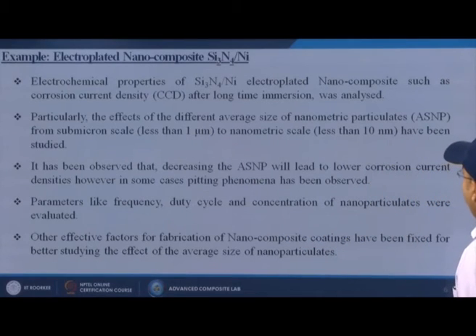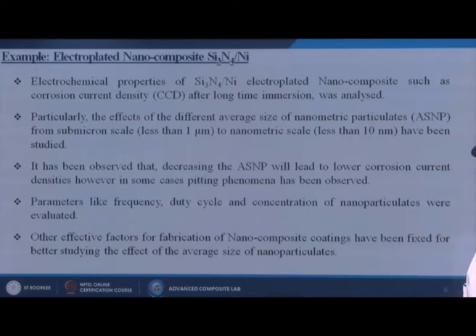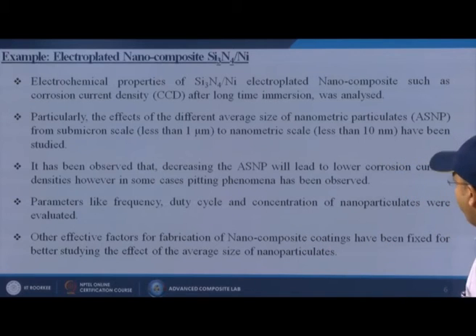Particularly, the effects of different average sizes of nanometric particulates, ASNP, from submicron scale, less than 1 micrometer, to nanometric scale, less than 10 nanometers, have been studied. It has been observed that decreasing the ASNP leads to lower corrosion current densities.